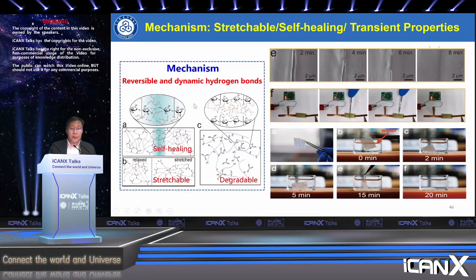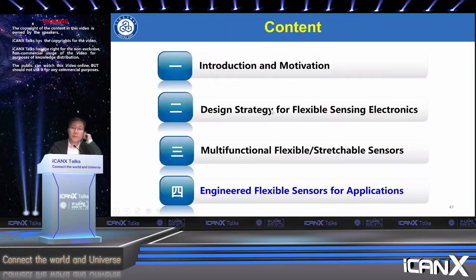glycerol into the hydroxyethyl cellulose, it forms a reversible and dynamic weak hydrogen bond, which gives it stretchable, self-healing, and also transient properties. Here you can see some demonstrations. When you put it in water, after about 15 minutes, these devices totally degrade.